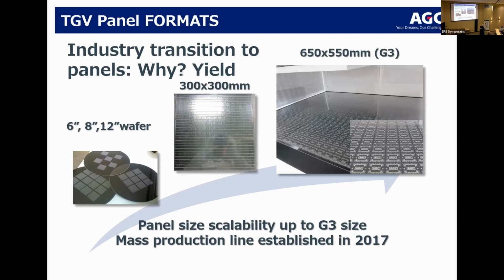If you have a die that's 5 by 5 millimeter, then your yield rate in a round wafer is around 65%. That's a lot of material to lose. In a rectangle or square panel, yields are approaching 85% to 90%. The difference is not 100% because of the streets. You have to factor in the loss of material there, and then there are the exclusion zones that you have to factor in as well.